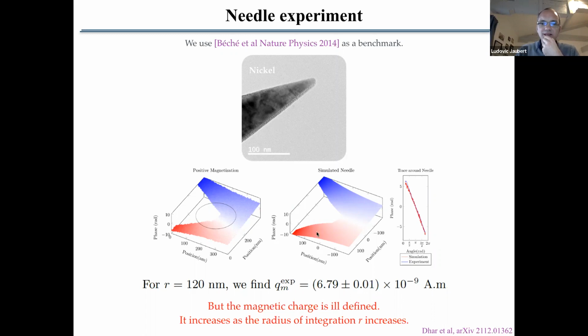And so you can see that this is the phase shift that you can measure. And because this part looks like a magnetic charge, you have a phase shift as you circle around it. And so if you do the integration around this contour, around this magnetic charge, you see that you have a ramp of the value of the phase. If you integrate it, you can calculate the value of this magnetic charge here at the tip.